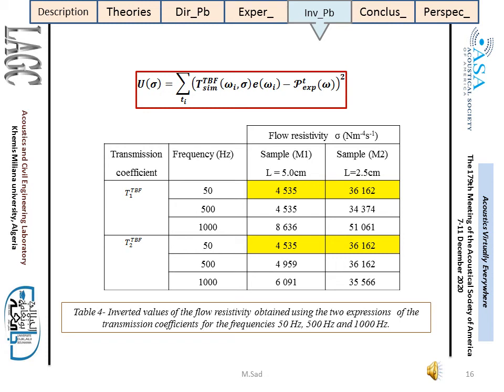After solving the inverse problem, it can be noted that the optimized values of the flow resistivity obtained by the two expressions T1 and T2 are identical at very low frequency. Whereas a slight difference is noted between the two inverted values of the flow resistivity using the two expressions T1 and T2 for the frequency 500 Hz. However, in all cases, the resistivity values are close to the values obtained by the direct method presented in Table 1.